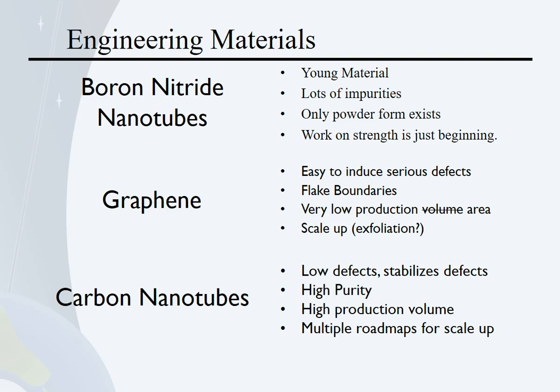Which brings us back to carbon nanotubes. We can already make them with few defects. We know how to stabilize these defects. Most nanotubes are actually what are called multi-walled nanotubes, so there will be multiple tubes nested within each other, kind of like matryoshka dolls. And these inner tubes will stabilize outer ones, even as they accumulate defects. So a nanotube can sustain a much higher amount of damage than we would expect intuitively before we see a significant drop-off in properties. We already talked about how they're self-healing.